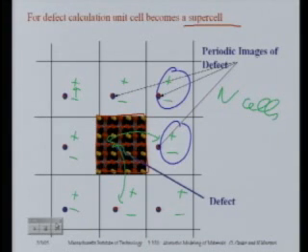Other things that often cause havoc is relaxation. If I were to put a really big ion in the center of that perovskite unit cell, I would build up a strain field, and the different defects would interact through their strain field. So rarely do you actually interact through the direct energetics. You often interact through secondary effects.